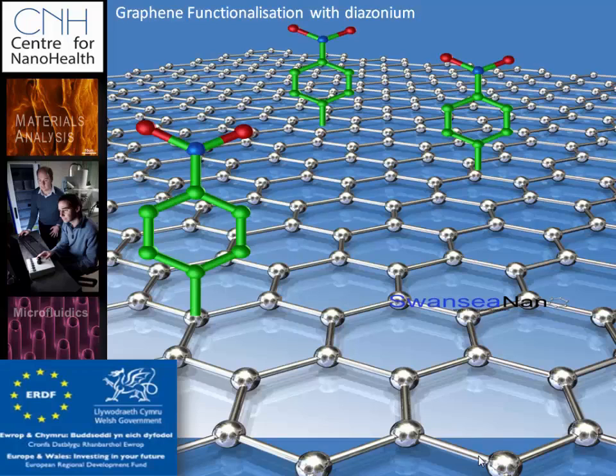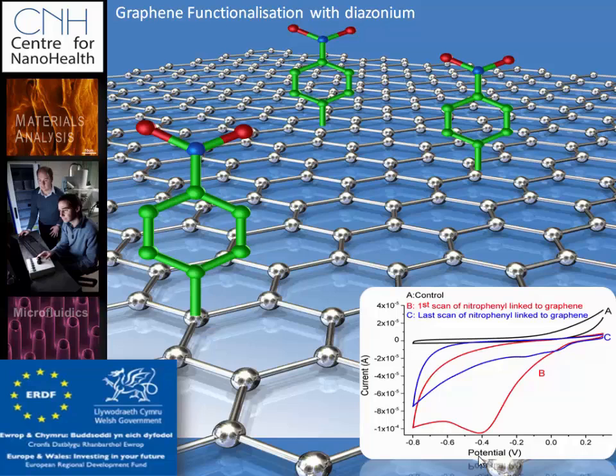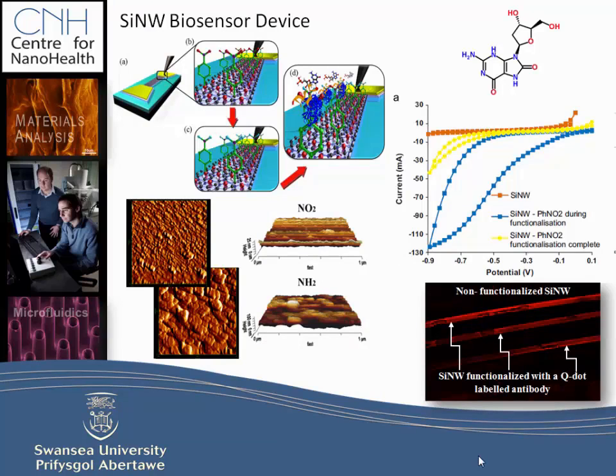This is the graphene functionalization process, and again, using a diazonium molecule to create an amino group on the surface, and we can then electrochemically functionalize that channel. So here are the channels, the functionalized channels. We've made these larger so we can use fluorescence microscopy to image labeled antibodies, and you can see the channels lit up quite nicely in red. We see changes in the AFM topography of the surface, and obviously we see changes in the cyclic voltammetry plots.